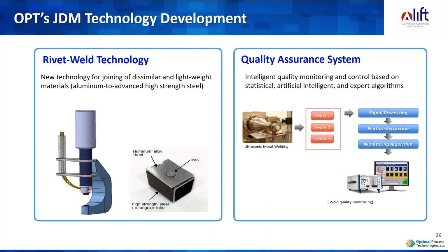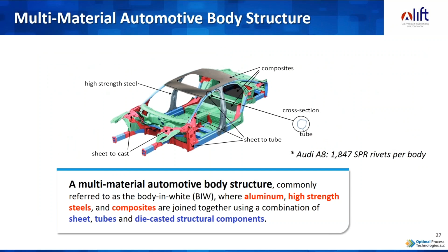The technologies that we have unique intellectual property on include a hybrid joining process known as the rivet weld technology, where we have the ability in a one-step manufacturing process to both rivet and resistance spot weld in an effort to join dissimilar materials. We can do this pretty effectively and have proven our ability to do it in a wide variety of material alloys and on different types of parts: sheet to sheet, sheet to casting, sheet to tube, for instance. We also have developed a rather unique machine learning weld quality assurance system that is particularly important for being able to measure, in a highly automated environment, a good weld versus a bad weld when welding dissimilar materials. Not only aluminum to steel, but aluminum to nickel and copper in the case of welding of battery tabs to bus bars.